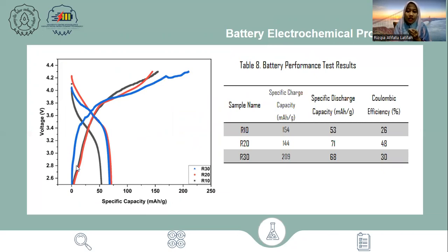The specific capacity and Coulombic efficiency produced are presented in Table 8. The highest specific capacity is 71 mAh/g, and the highest Coulombic efficiency is 48%. The capacity and the Coulombic efficiency are still low because the lithium nickel manganese cobalt material has not been formed properly. The difference in particle size causes the ion diffusion process to be hampered, so that there is a loss of specific capacity at the anode and cathode.